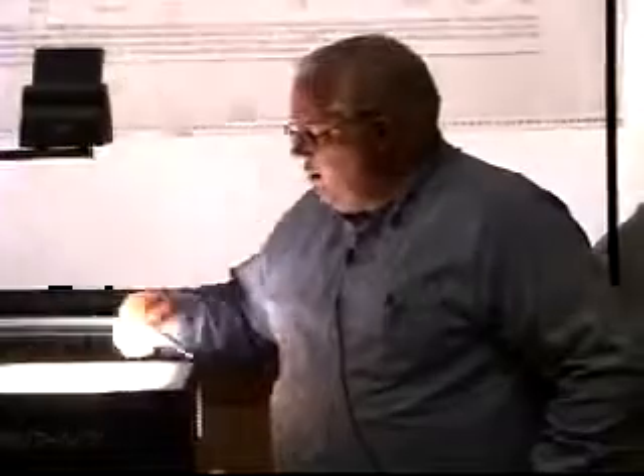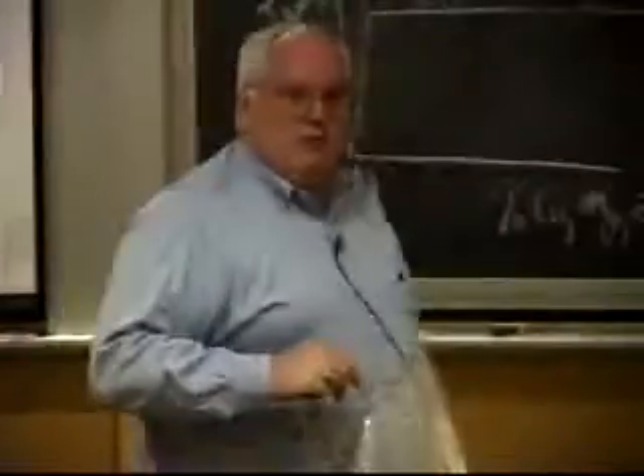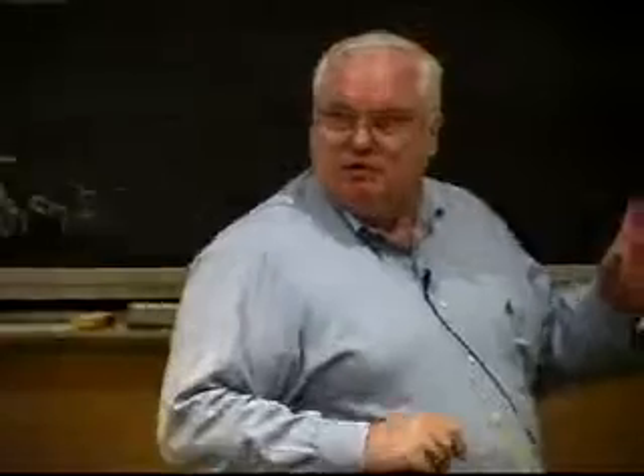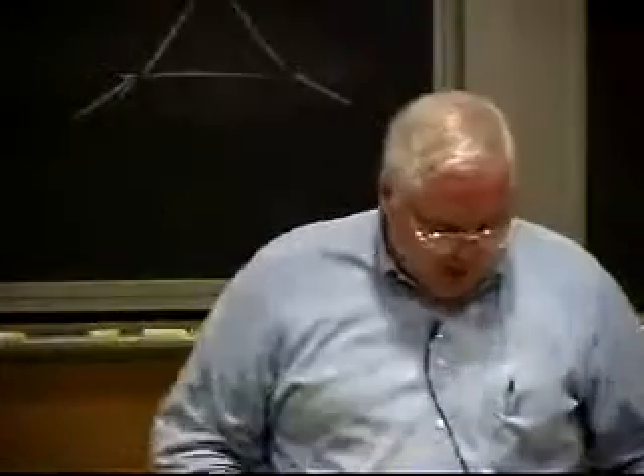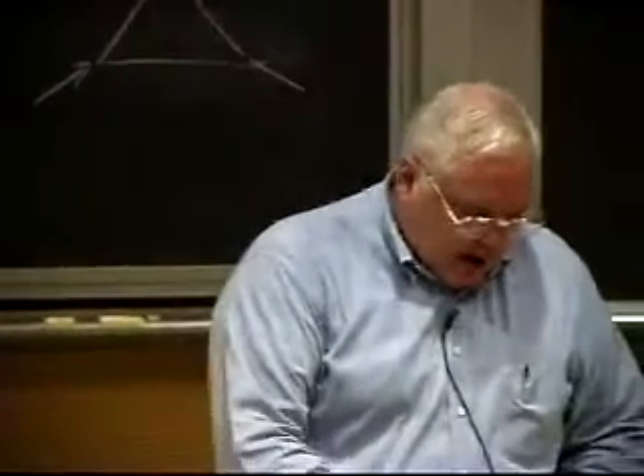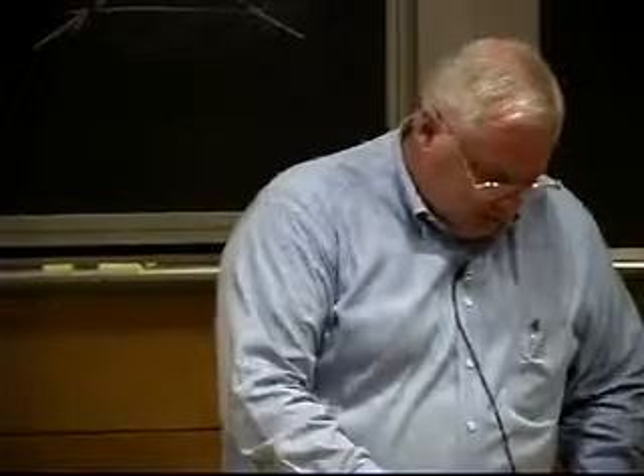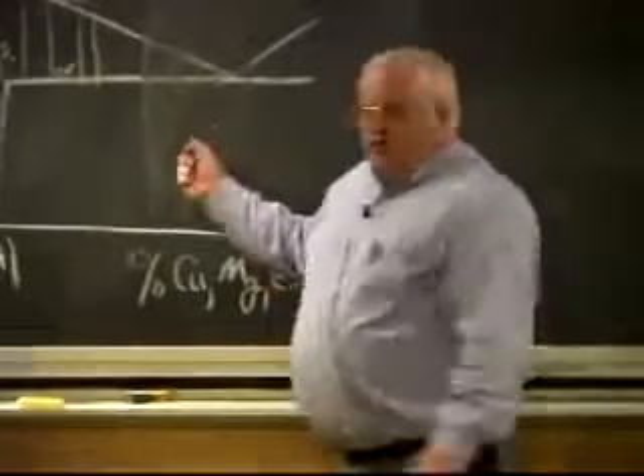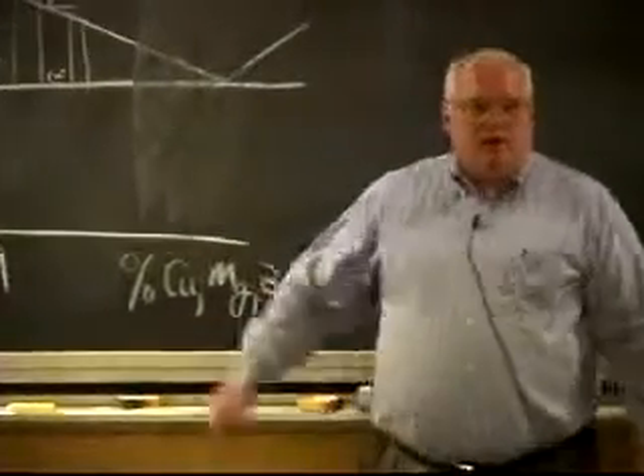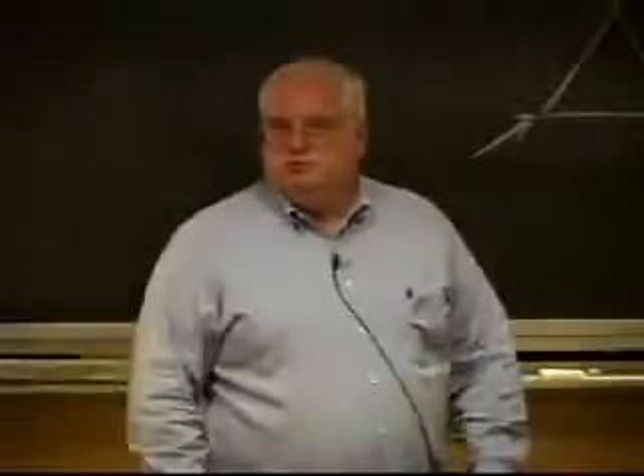And if you were to look at some of the other alloying elements, you'd find similar types of things. But this is just illustrating, if you look at aluminum alloys, you'll see the gap between the lightly alloyed and the highly alloyed aluminums. Turns out most of your aluminum casting alloys are the very heavily alloyed, way over here. Why? Because they're lower melting. It's easier to cast, and you can get some pretty good properties in them.